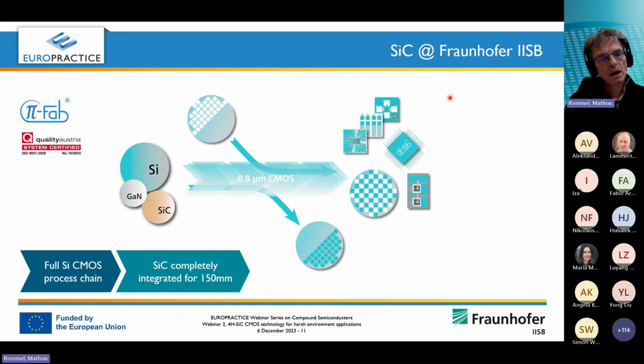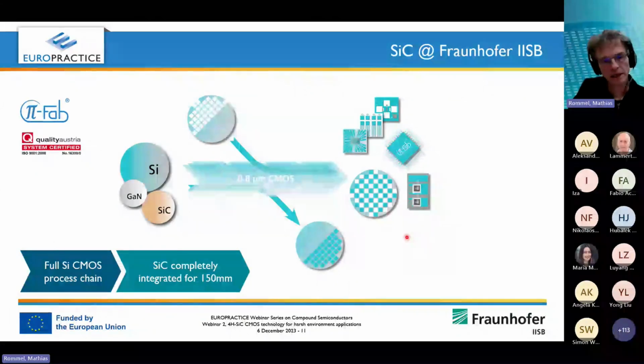Last slide. What do we have? We have a full silicon CMOS process chain as well as a full silicon carbide CMOS process chain operated in one clean room, and that's what I somehow indicated already before, that we can use a lot of equipment and also even processes for both technologies. But of course, if it goes to, let's say, annealing or activation of the doping, of course, we need quite different temperatures if we operate silicon carbide or if we operate silicon. But in principle, we can use the same clean room.